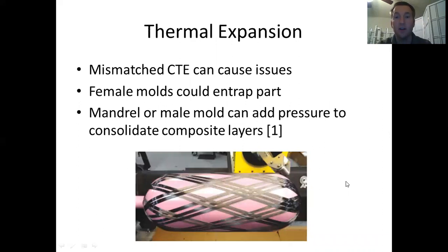Another factor is the thermal expansion. If you're heating the mold, you can have a mismatch in the coefficient of thermal expansion between the composite and the polymer mold. So if your mold is shaped as a female part where your composite is inside, that expansion and contraction could trap your part inside of the mold. So a better approach would be to create a mandrel or a male molded piece. And then you can actually use that expansion to your benefit, because the expanding polymer will add pressure to your composite layers and help to consolidate them.